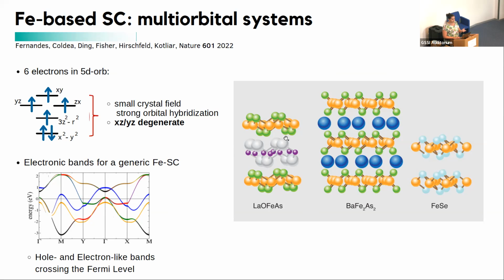And as James actually mentioned, all the families share more or less the same structure with this iron arsenide or iron selenium layer, and the electronic band is quite the same. You have hole pockets and electron pockets at different points of the Brillouin zone.